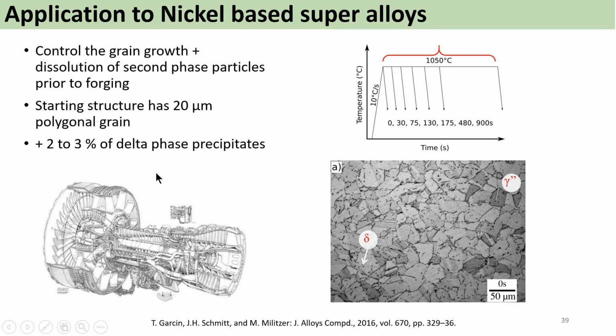This type of alloy here is Inconel and is used in parts of aircraft engines. And those alloys contain small precipitates. They are called delta precipitates here, which will dissolve during the homogenization treatment of those alloys. And the dissolution of this precipitate needs to be controlled very accurately because it will affect the grain growth of the matrix phase. And if the dissolution occurs heterogeneously, then we will have again the presence of abnormal grain growth.